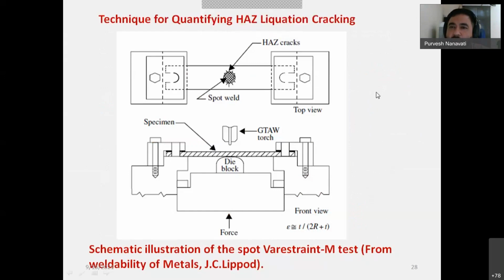I'm trying to use the cursor. Okay, it automatically went up. Now you would see that only a spot weld is made, right? Now you must be seeing that there is an HAZ crack. So this is a more accurate test to judge the susceptibility of cracks in the heat affected zone in comparison with the previous test, the transverse test, right?